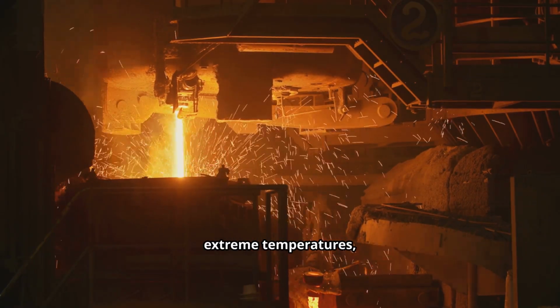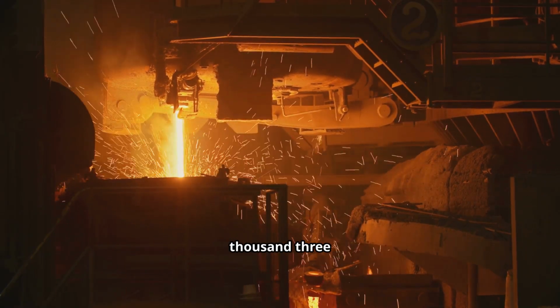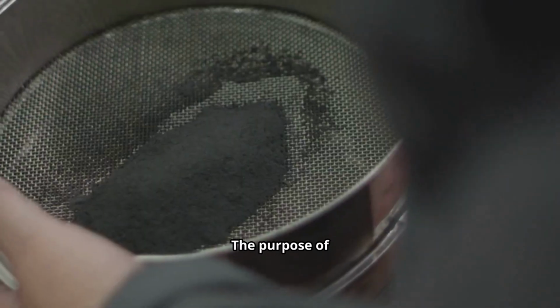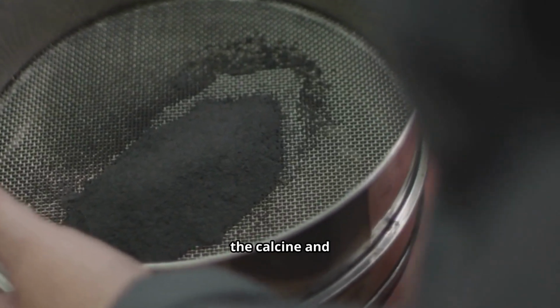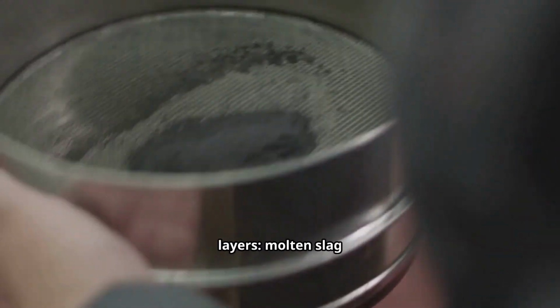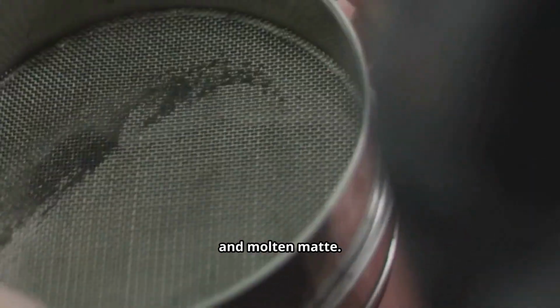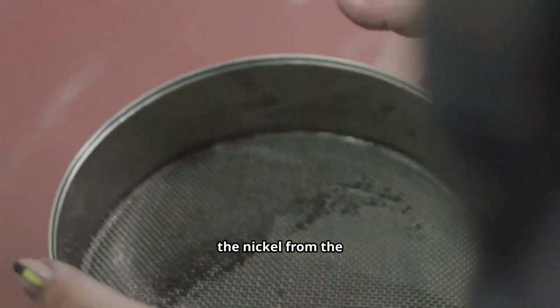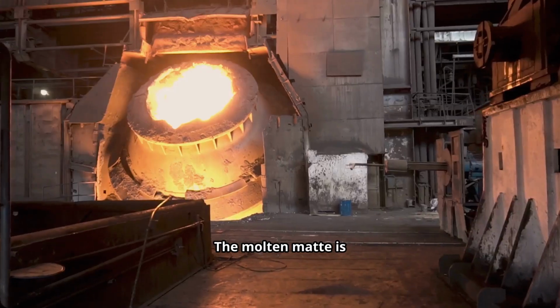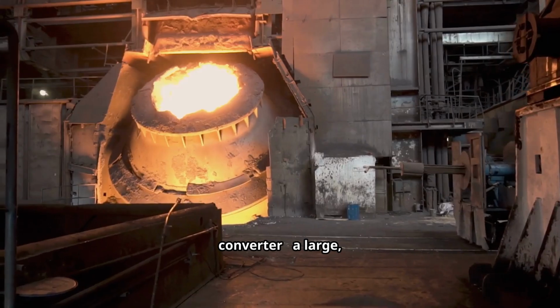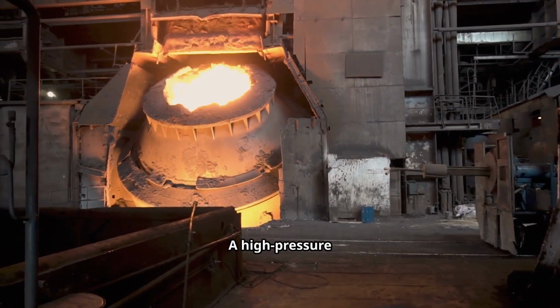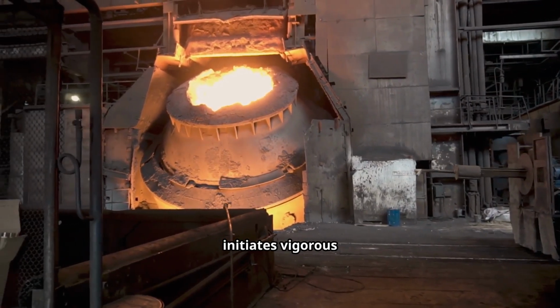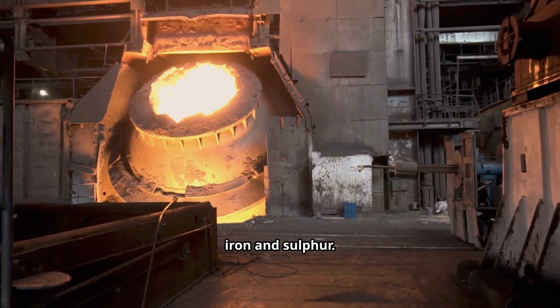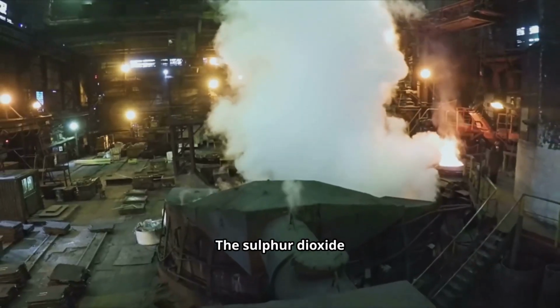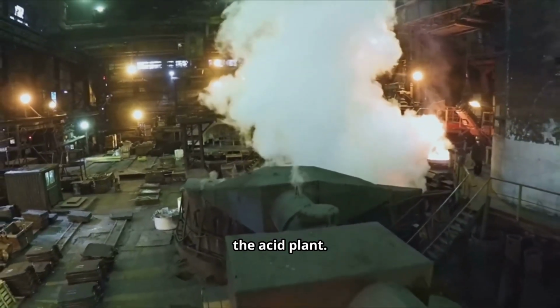It is heated to extreme temperatures, often exceeding 1,300 degrees Celsius. The purpose of smelting is to melt the calcine and separate it into two distinct liquid layers, molten slag and molten matte. The matte contains the nickel from the original concentrate. The molten matte is poured into the converter, a large pear-shaped tilting furnace. A high-pressure blast of air initiates vigorous chemical reactions to remove remaining iron and sulfur. The sulfur dioxide gas produced is captured and sent to the acid plant.